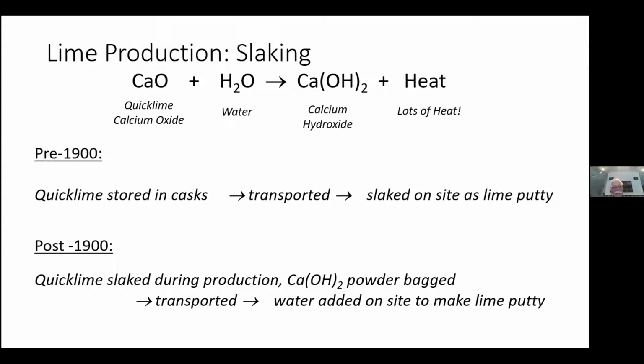After about 1900, chemical engineering types of processes started to come on board, which allowed the lime to be combined, I typically think, using steam with exactly the amount of water needed to produce calcium hydroxide, which itself is a whitish powder. And the powder then could be bagged and transported. Later, if they wanted to make a lime putty out of it, they would just combine it with water. The difference between these two is when the slaking of the lime takes place. The advantage of working with calcium hydroxide is that you avoid this big loss of heat which is produced when the lime is slaked. So that's done in a controlled fashion rather than an uncontrolled fashion.